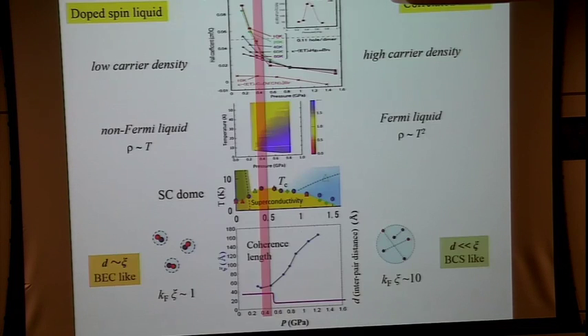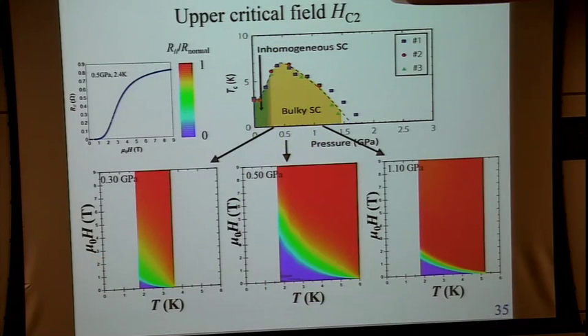Yes? So can you go to the previous one? Yes. It's a very important point. We measure the superconductivity by AC susceptibility measurements. But in these regions, superconductivity is not complete. Maybe at ambient pressure, the fraction of the superconducting volume may be 30% or something like this. But I'm not sure about the reason. However, under pressure, the superconducting volume fraction becomes full, 100%. So this inhomogeneity, I think, may be an intrinsic property.